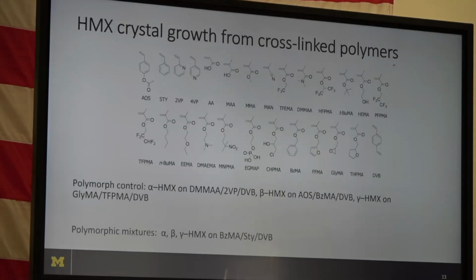But we got these things, and so I started looking at these large libraries of polymers and growing by heteronucleation on these polymers, different polymorphs of HMX. And indeed, you can selectively get the alpha, beta, or gamma. Now, those were all known, but the way they're typically made is by varying the solvent or the temperature, or sometimes there are kinetic conversions that can occur. So here we're doing all of this discovery from one solvent under one condition, just evaporation.